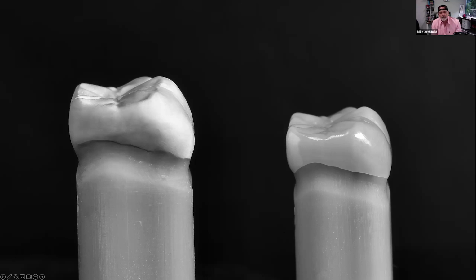One of the unlocks with this process is the small particle size of the nano zirconia. The particles are actually the size of tobacco smoke. They are very, very small, fine particles. And nano zirconia is a binderless zirconia. There are no binders used in the manufacturing process. So these particles have a really high density. That's why you'll notice the shrinkage rate of the nano zirconia is less than the shrinkage rate of the average isostatic press zirconia.